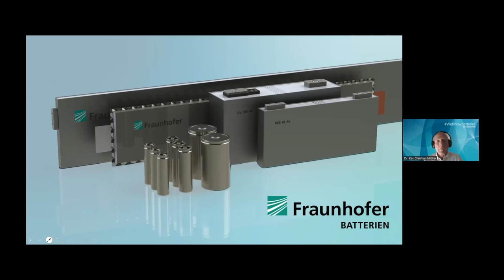And the switch is to get from organic toxic solvents to water, which is not possible with all cathode materials because they can leach out the lithium and will not work as expected. And then you have to coat the slurry very exactly on the metal foil with a defined thickness. You have a drying process after the coating, which takes a long time and a lot of energy to dry the electrode and recycle the solvent again.